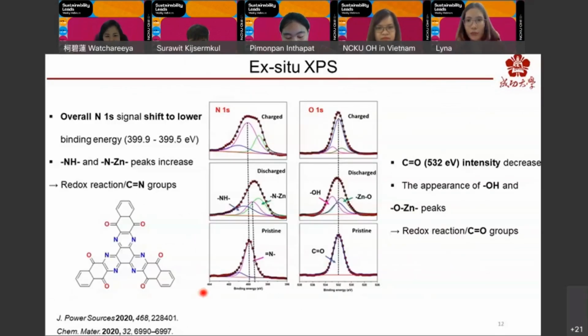To unravel the reaction mechanism, ex situ XPS was examined. At the end of discharge, the new signal appeared, indicating the insertion of ionic charge carriers, and these signals decreased in intensity at the end of charge, suggesting the extraction of the ionic charge carriers.